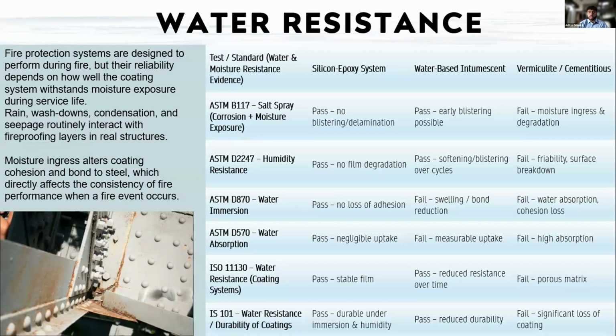And then ASTM D2247, humidity resistance, important for application in coastal areas. The silicone epoxy system passes with no problem, and the water-based intumescent coating passes with softening or blistering over cycles, and the vermiculite coating fails. Then ASTM D870, water immersion, where you dip the sample in water, and silicone epoxy had no effect. It passes the test. Water-based fails that test, as well as vermiculite. And ASTM D570, water absorption. Silicone epoxy absorbed negligible water, and water-based failed that test, as well as vermiculite.